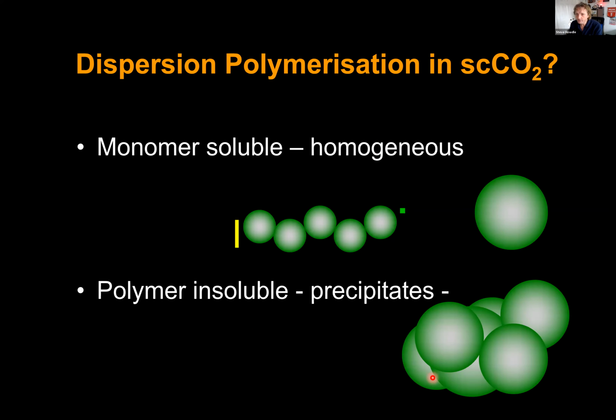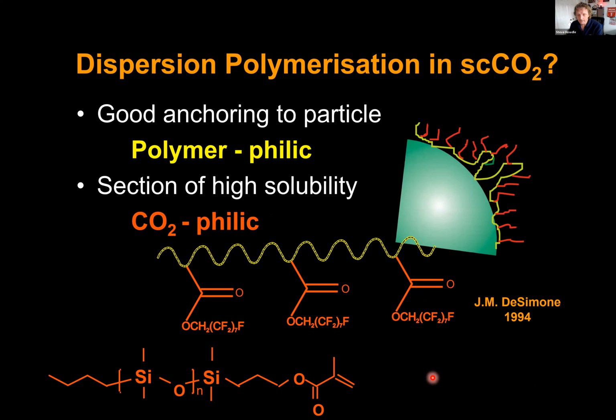But you can avoid this precipitation if you add the right stabilizer or surfactant or detergent. And in CO2, these had been created. My group made quite a lot of silicone materials, and Joe DeSimone in the USA started out by making some very nice fluorinated ones. The surfactant simply sits on the surface of the growing polymer particle and prevents them from sticking together, and that means that the dispersion polymerization works very effectively.